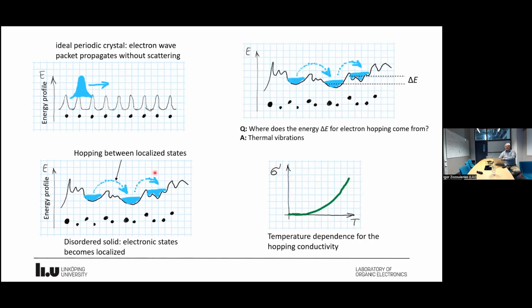One can ask what actually determines the efficiency of the hopping. Where does the energy come from? For example, if an electron is sitting here, it has to jump there, so it goes up in energy. Where does the energy come from? The answer is that the energy comes from the thermal vibration of the lattice. Therefore, the temperature dependence of the conductivity would look like this. At low temperature it will be very small because there is very little thermal vibration, but then it will increase with the increase of the temperature.